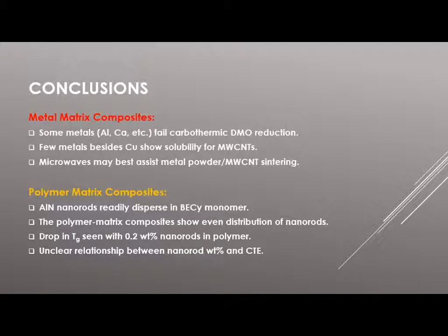And then we also found that few of the metals, besides copper, are showing solubility for the nanotubes. As illustrated before, only the copper had a distinct metal matrix composite that we found in it, and we weren't really detecting carbon in these other samples as well. That was the main indicator here that we didn't have metal matrix composites. And so, as we also realized in looking at the data, these other metals just don't have high solubility for carbon, but copper does have better solubility.